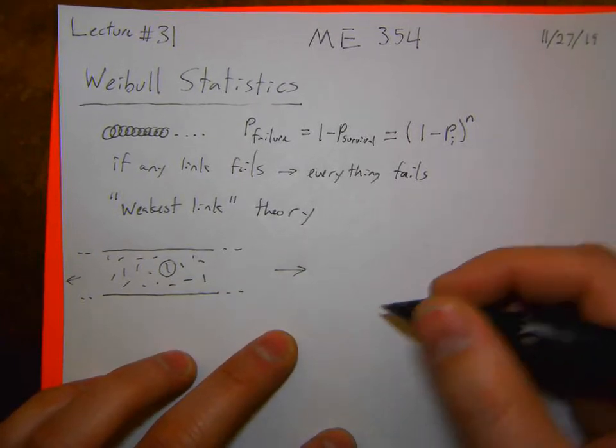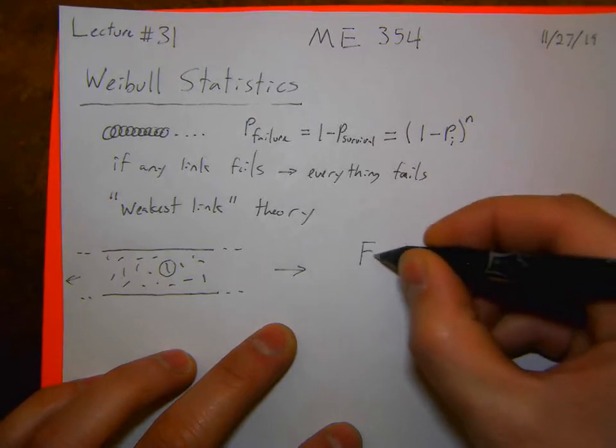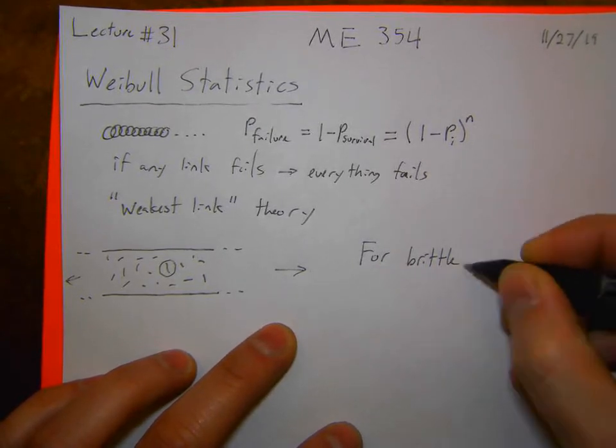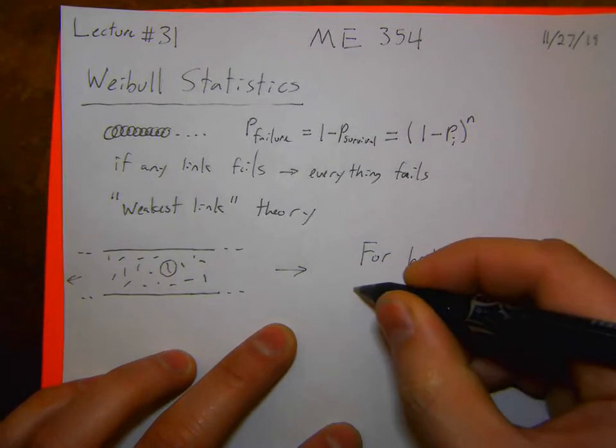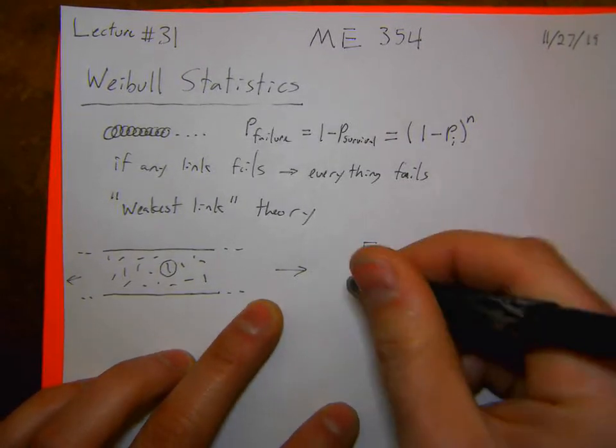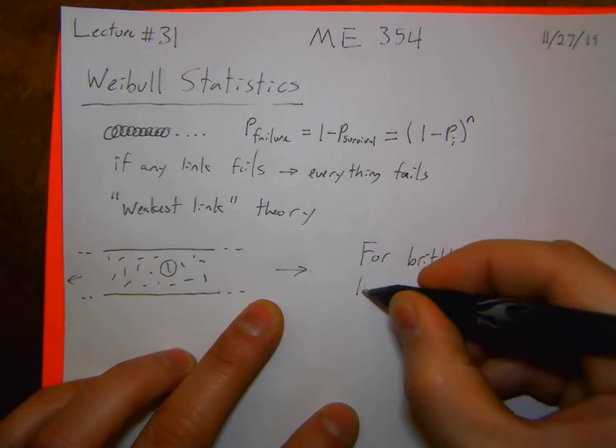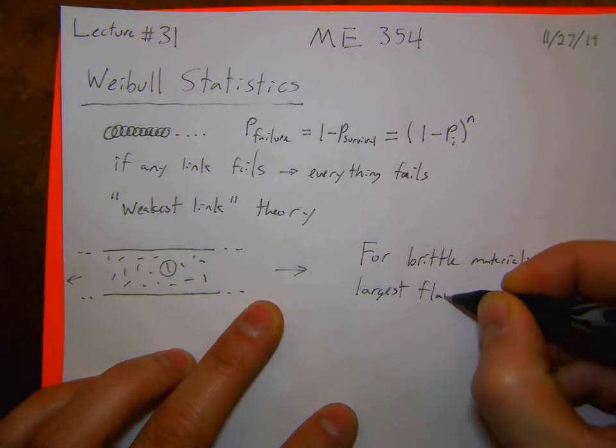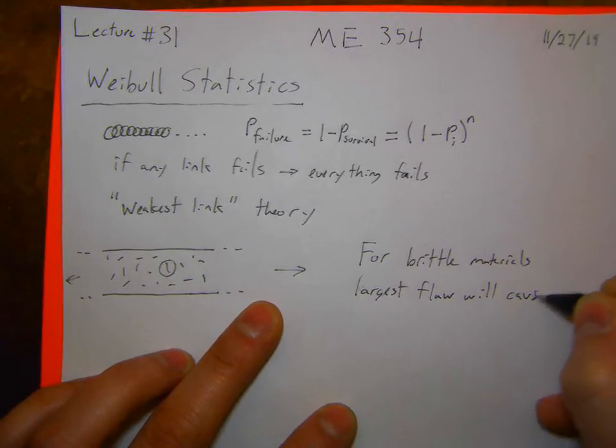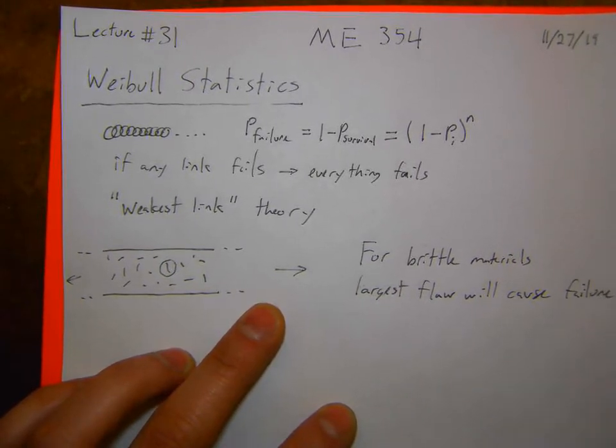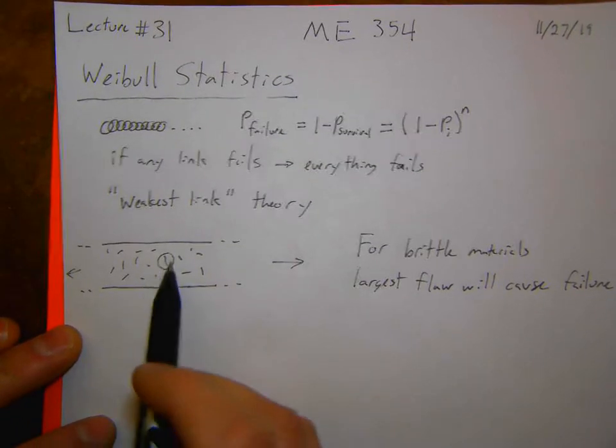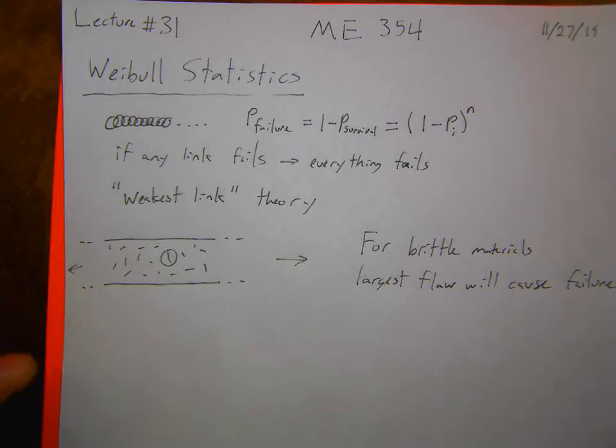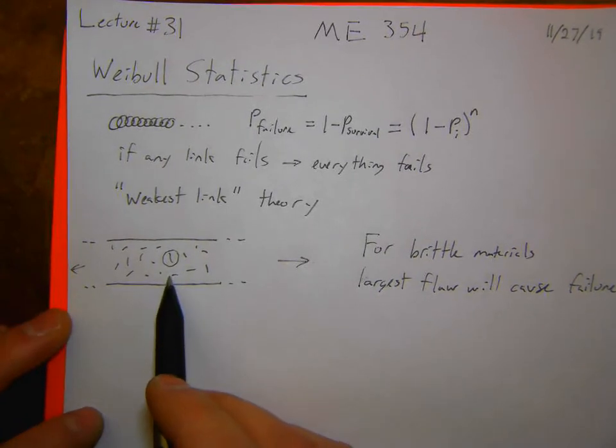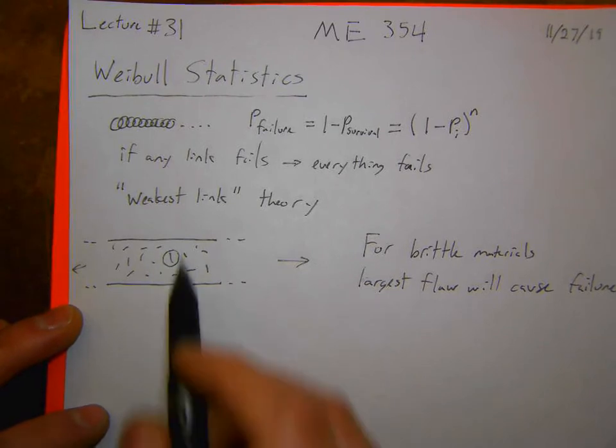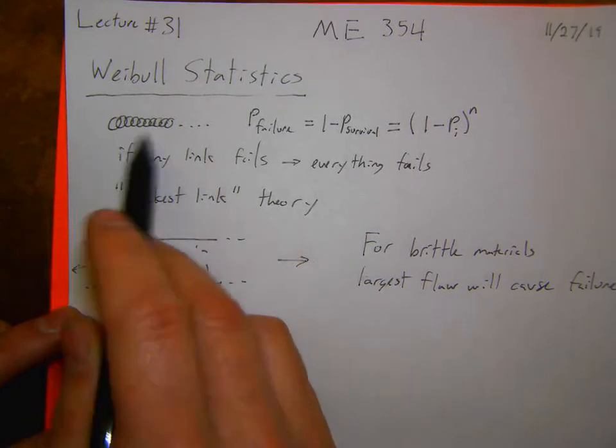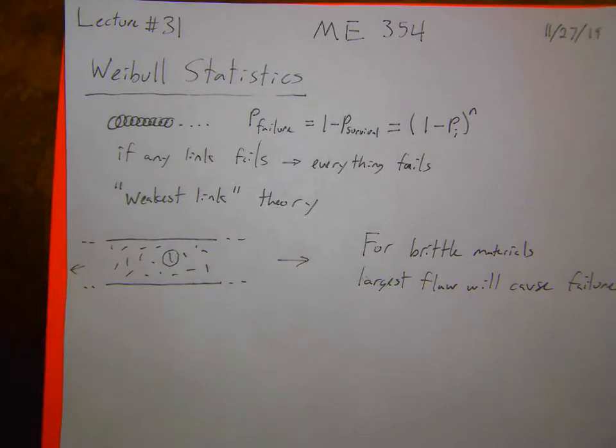So now for brittle materials, we're looking at the largest flaw size that's going to cause failure. So it's going to be the weakest point in my fiber, in my ceramic plate, in my whatever, that's going to cause this thing to fail. And once that starts to go, it'll propagate through the rest of the structure, similar to how in a chain link, if I have any one of those links fail, the whole chain fails.